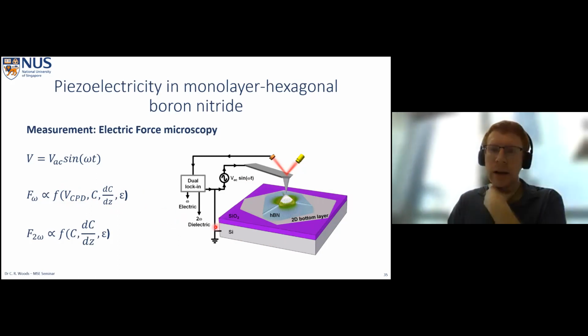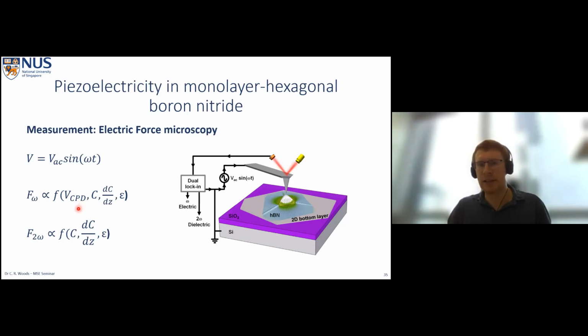But thankfully, we can decouple a lot of these parameters by looking at both the first harmonic of the oscillation of our tip and the second harmonic. The second harmonic is sensitive to the capacitance, how the capacitance changes with Z, and the dielectric, whereas the first harmonic is sensitive to all three of those plus the CPD. And this is the one we're going to want to be looking at, the CPD. So if we can see something in our first harmonic, but we don't see it in the second harmonic, we can isolate it as being a force due to the contact potential difference, or just the potential difference between our silicon and our tip.